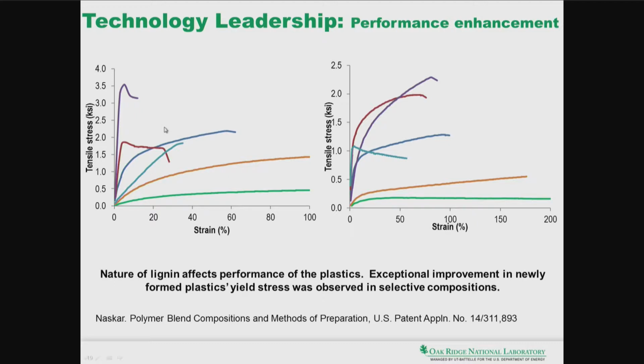Now, as you can see, this is a group of lignin that work that way. Now, when we applied the same chemistry on another group of lignin, we don't see that kind of improvement in mechanical property. Rather, some of these additives reduced the mechanical property, and the material became again rubbery. So our additive is almost like a plasticizer for some lignin, and for some lignin that is a strength enhancer. So that's where we believe lignin structure and properties are contributing to the mechanical property, and that gives some new product that has sometimes yield stress.